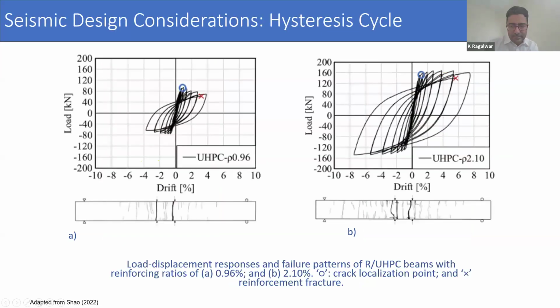So this is what I was talking about. You see, these curves are fuller, but if you have seen conventional concrete under cyclic loading, once the load cycle reverses after the peak, we would have seen not a steep or straight increase in the load, but it kind of goes this way before it picks up the load. So there is some initial displacement, which is basically equivalent to closing of those wide cracks that happens in normal concrete. That here is not seen, and that's why we get fuller curves, and the energy dissipation is equal to the area under these hysteretic loops. So the larger the area, the more energy is dissipated, and that's why these are able to dissipate higher energy events as well.